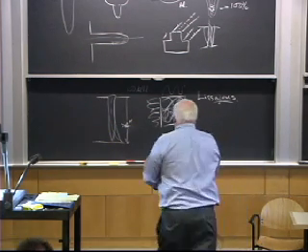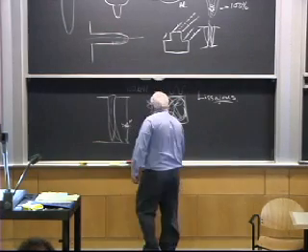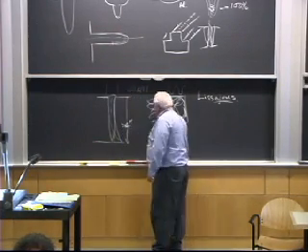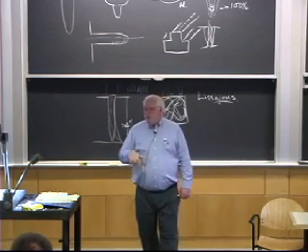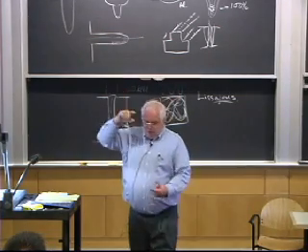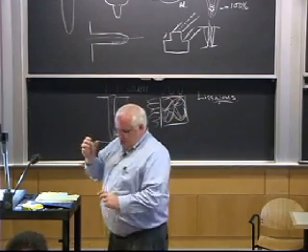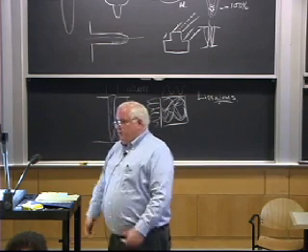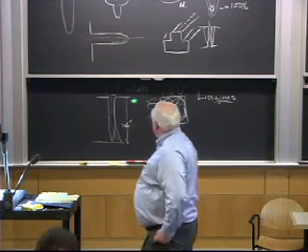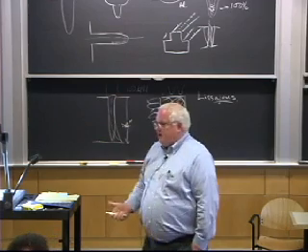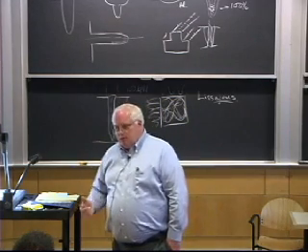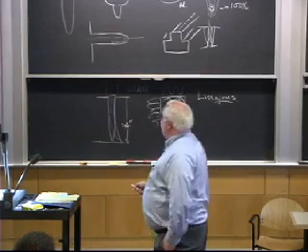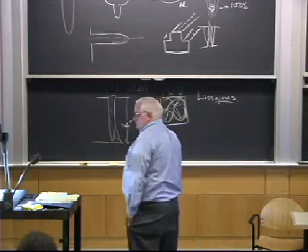Another problem is if there is an external field, the beam could bend before it ever gets here. Well, they got a simple solution to that. You just shoot it through a pipe, okay? If you're generating the beam up here and your workpiece is 2 feet away, you just put a 2-inch diameter steel pipe around it and shoot it through that pipe, even if you're in a vacuum. And that steel pipe will shield the unbalanced magnetic fields enough that the beam will go through there straight. So anyway, an electron beam is distorted by magnetic fields.